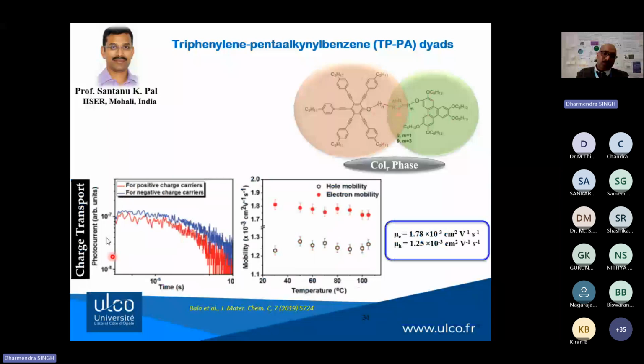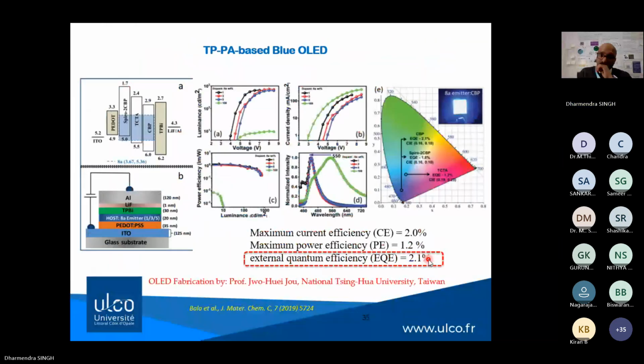So you could see here, obviously due to the bulky nature of the molecule, the photocurrent curve was very noisy. However, because centrosymmetry was not broken, we observed temperature invariant charge carrier mobility in the order of 10 to the power minus 3. This compound was really very interesting because we observed ambipolar charge carrier mobility corresponding to electron and hole. Obviously, the electron charge carrier mobility was a little higher in magnitude as compared to the holes. And why this compound was very interesting, because this compound was later used to fabricate the blue LED. And this was the first report for the fabrication of blue LED using discotic material.